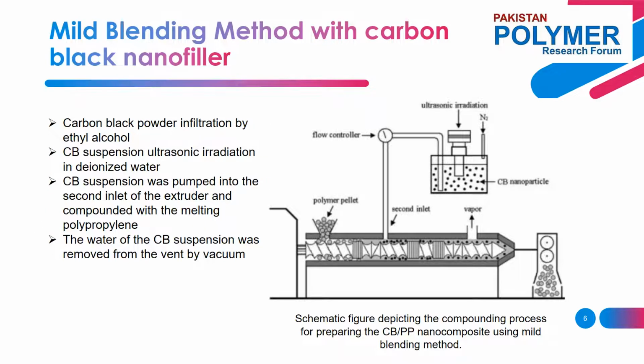The first study is the preparation of carbon black and polypropylene nanocomposite with a low percolation threshold using the mild blending method. In this study, a new approach, the mild blending method, was reported to prepare carbon black filled polypropylene nanocomposite. Carbon black suspension was prepared by dispersing the carbon black powder into deionized water using ultrasonic irradiation for 10 minutes.